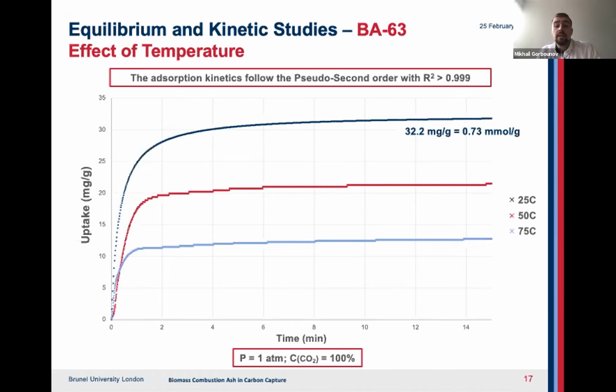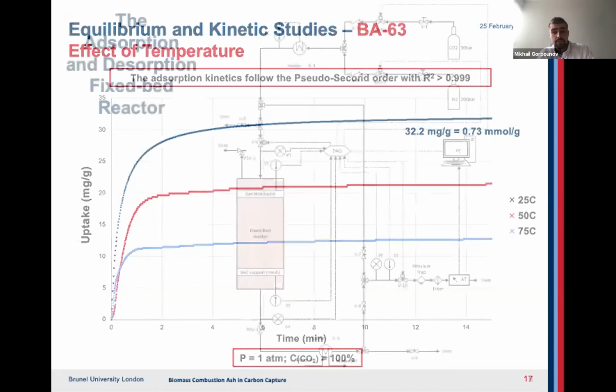Additionally, we have looked into determining the effect of temperature on the equilibrium capacity, and here, as expected, the uptake follows the general trend for adsorbents to perform better at lower temperatures, with the kinetics following the pseudo second order with an R-squared value of over 0.999 for the investigated isotherms. We will also, in the upcoming days, investigate the influence of flow rate and gas composition on the adsorption of our BA63, as well as look into the issues of mass transfer.